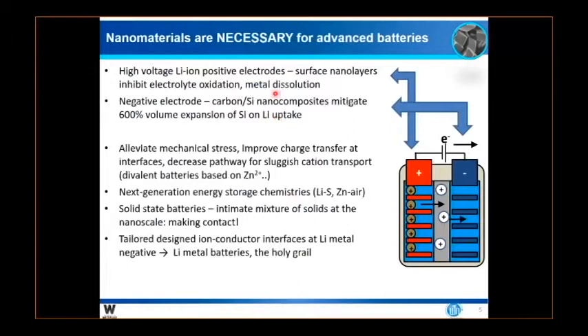So as I mentioned, nanomaterials are actually necessary for advanced batteries, not the sort of traditional ones that we have today. And even in the traditional ones that we have today, at the positive electrode, we have materials which, as I said, are sitting at a very high potential, and they require surface nanolayers to inhibit the electrolyte oxidation. So these are actually produced more or less in situ by the careful reaction of these electrolytes that are designed to produce such layers. And they don't really work very well, but they work as best as possible.